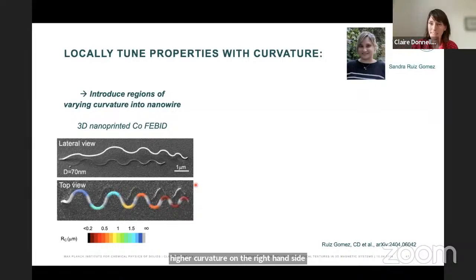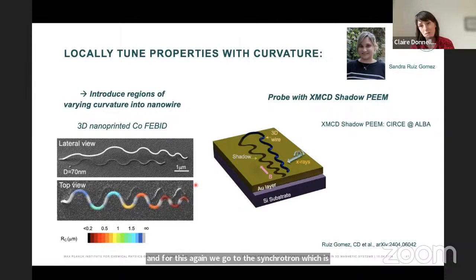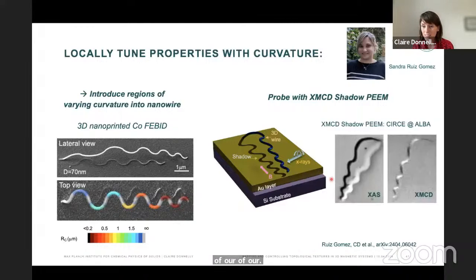We, of course, want to image the magnetic configuration. And for this, again, we go to the synchrotron, which is our measurement technique of choice. But this time, rather than doing 3D imaging, what we perform is XMCD shadow PEEM. So essentially, the idea is that our nanostructure is suspended above the surface. And if we come in with the X-rays at a shallow angle, we can image the shadow of the X-rays on the surface of our substrate. In this way, you can see here that the bright part is actually the structure, but the dark part here is the absorption of our nanostructure. When we take XMCD, we can directly image the magnetic configuration in this way.